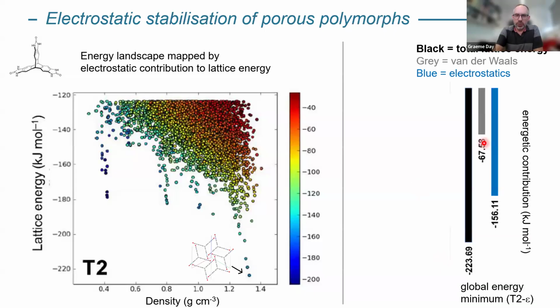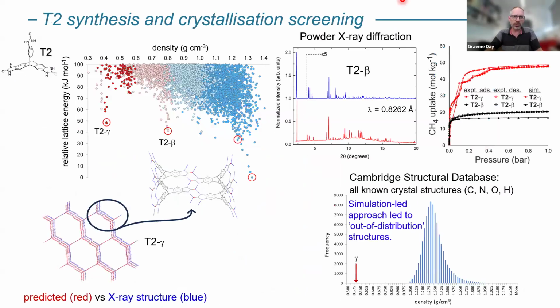In this case, one thing we wanted to target, if we go back, is this T2 gamma polymorph here. It's a nice thing in that it's very porous. It can absorb the amount of methane that we want. But if you compare it to this red circled structure here, that's the global energy minimum, and that's a close packed structure. It's non-porous. This T2 gamma is about 50 kilojoules per mole up from that global minimum. And the reason we can get it is because it gets kinetically trapped during crystallization.